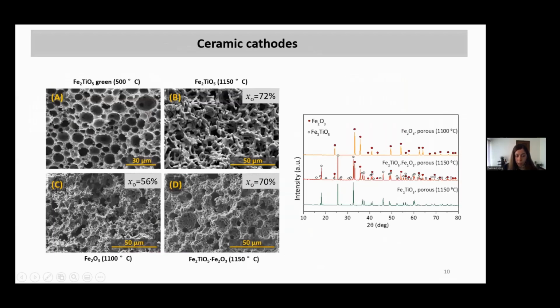These are the designs of the ceramic cathodes. The first image is the green monoliths of pseudobrookite after burnout of the paraffin. It's very fragile, and you can see clearly the open porosities. We fire it until 1,150 Celsius degrees. You can see it's very porous still. It has interconnectivity between the pores and has an open porosity of 72%. We did the same procedure for hematite and for the composite, and we obtained around 56% of open porosity and 70% in the case of composite. The pseudobrookite is single phase, as you can see here. We have only segregation of hematite in the case of the composites, as expected.